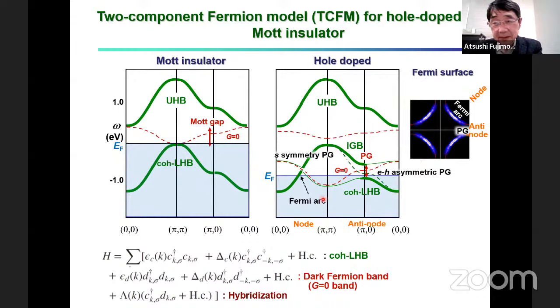And this formalism is more flexible in that the pseudo gap can also open in the nodal region. In the D-wave gap, the gap is zero on the nodal line, but in this formalism, a nodal pseudo gap can appear at the node also like this, but the pseudo gap reaches the Fermi level only in the antinodal region. So that's why we observe this pseudo gap structure. And the effect of superconductivity is introduced by a pairing potential, and the superconducting gap opens here.